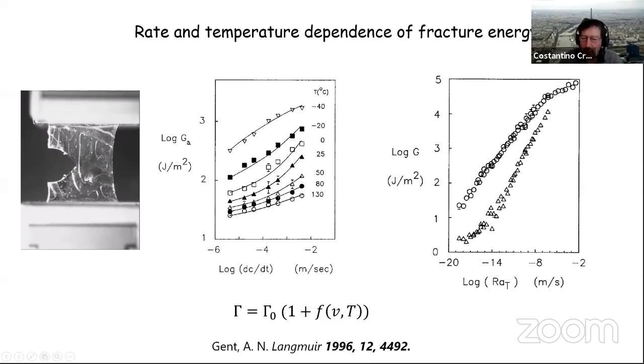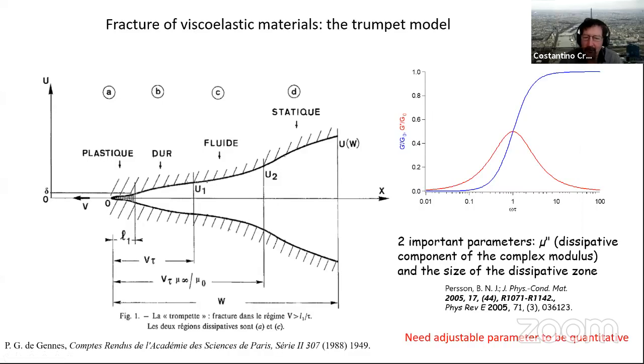And this type of model has been built using linear rheology. This is an older version by de Gennes, much more qualitative, where he was arguing that indeed you could explain the rate dependence of fracture in that way from linear rheology, and he predicted some dependence. There is a much better description in a nice review paper by Persson and also another paper where he explains how you could predict fracture energy from mu prime and mu double prime from the linear viscoelastic property.